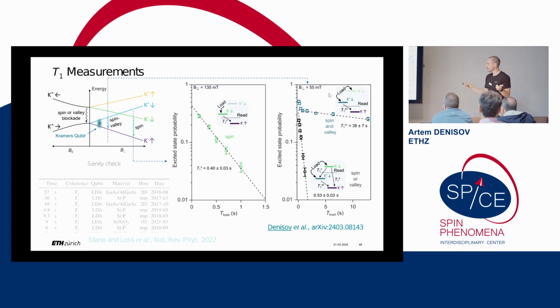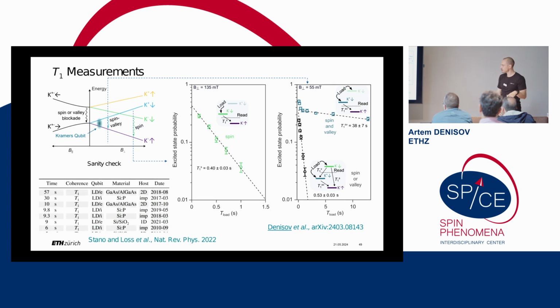And if you look at the table of the longest T1 times ever measured, first of all, the funny thing is that the longest time was measured in gallium arsenide in Basel. And in this way, our result goes here as second. But we don't think that 38 seconds is what limits our results, because what really limits it is how much time you can spend in the lab. In order to acquire 1,000, 2,000 shots with 38 seconds each, you need more than 15 hours, which is just not feasible. And also your device every few days can switch due to some random telegraph, very low frequency noise because of the semiconductor.